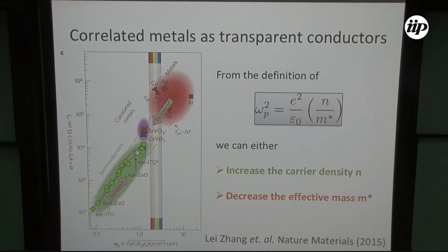So as I said, people normally try to go up this hill here. Why? Because the main object here is the plasmon frequency. We cannot change e squared, we cannot change epsilon 0, but we can change N or m star. So if you have a light mass semiconductor, like for example ITO, which has a very small effective mass, it has a rather large plasmon frequency. But if you can start increasing the carrier concentration, you are going in this direction.